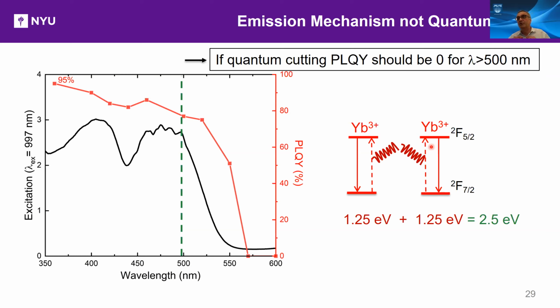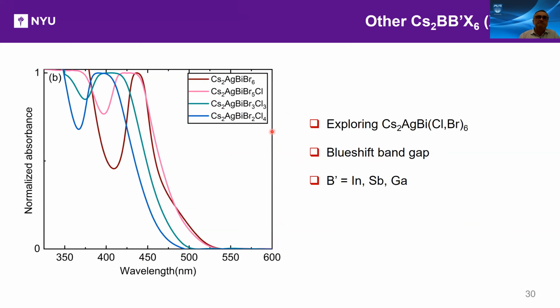There could still be quantum cutting happening in the material, but most of it is not quantum cutting. And the reason for this is that beyond 500 nanometers, we still have photoluminescence quantum yield, or emission from the infrared. The significance of that is that to have two of the ytterbium excited at once by quantum cutting, you need 2.5 electron volts, and that's that threshold. What I'm showing you here is photoluminescence quantum yield beyond that, and then going to zero at the band gap. So definitively, we can say that there is sort of garden variety down conversion, not quantum cutting, happening.